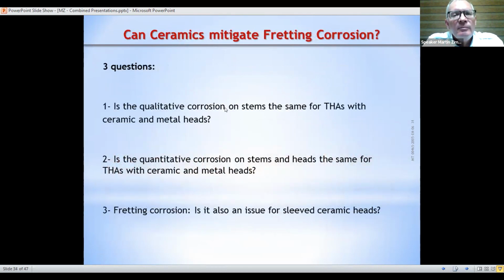So the question that we ask ourselves at CeramTech: can ceramics mitigate fretting and corrosion, knowing that the ceramic ball head is much harder than cobalt chrome, as I demonstrated before? Does it create more or less fretting corrosion at the surface of the taper of the stem?